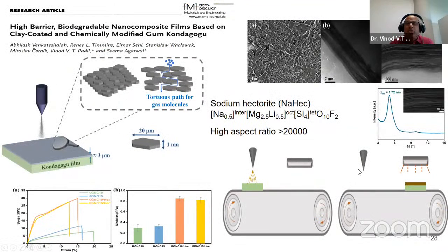And the next important section is the synthesis of high barrier and biodegradable films based on clay-coated chemically modified gum kondagogu. You can see here we used sodium hectorite in addition to the gum, so it can form very nice nacre-like structures and improve hydrophobicity of the film and mechanical and other barrier properties. This has been reported recently. We published this work in Macromolecular Materials and Engineering.